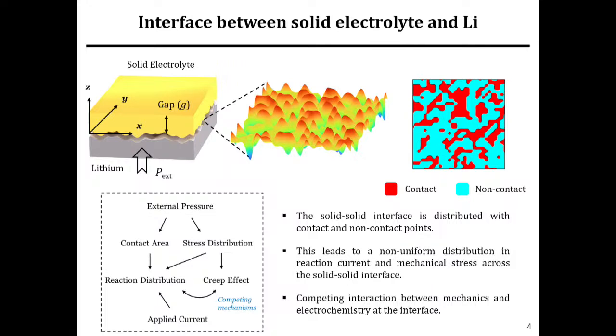Because of the surface roughness of the solid electrolyte and lithium metal, when they are compressed externally, this results in the origin of mechanical stresses. These mechanical stresses fundamentally alter the ionic transport behavior and electrochemical reactions that occur at such solid-solid interfaces. This is a key characteristic of solid-solid interfaces: they exhibit a mechanistic coupling amongst the various electrochemical, transport, and mechanics processes that take place at these interfaces.